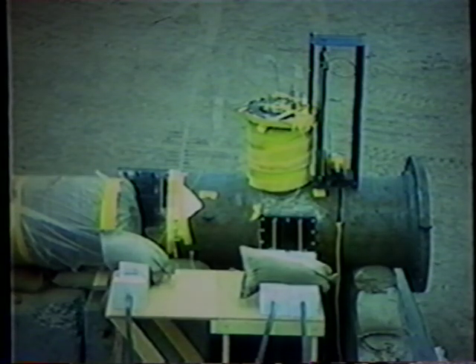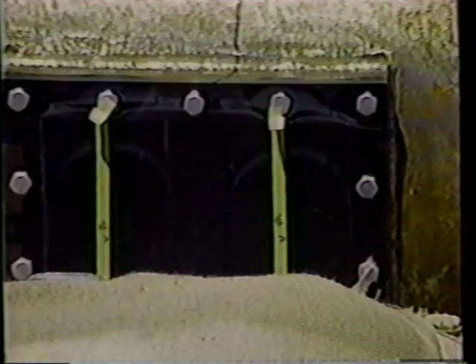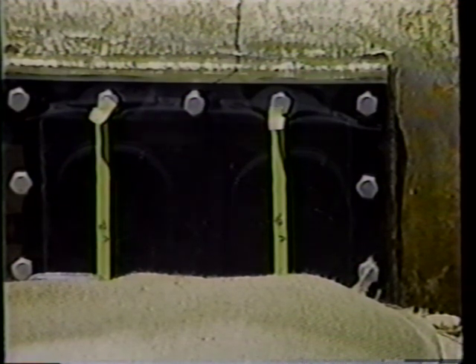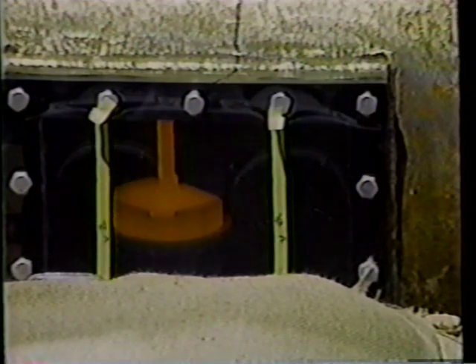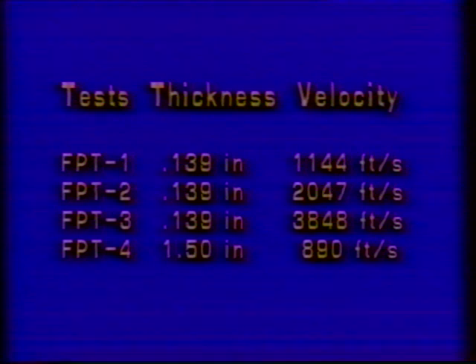4 flyer plate tests evaluated what would happen if a plate-like projectile hit the fuel capsule flat on. For this test sequence, the simulant fuel capsule is heated to the proper temperature and lowered from the furnace so that it faces the aluminum flyer plate. The plate is driven into the fuel capsule by an explosive charge mounted on the back side of the plate. Depending on the thickness of the plate, the velocities for cladding damage ranged from 890 feet per second to over 3,800 feet per second, well beyond the flyer plate velocities predicted by Titan Centaur tests.